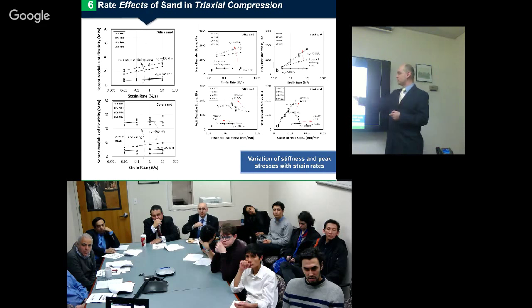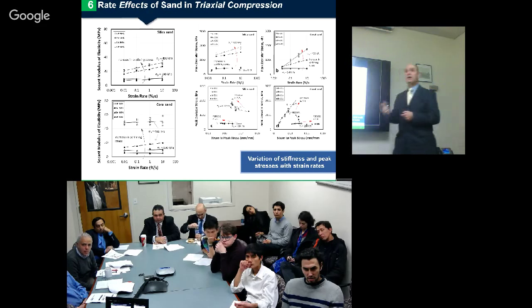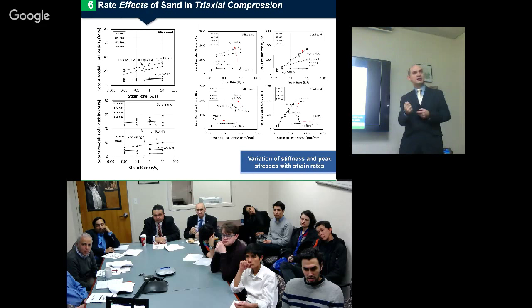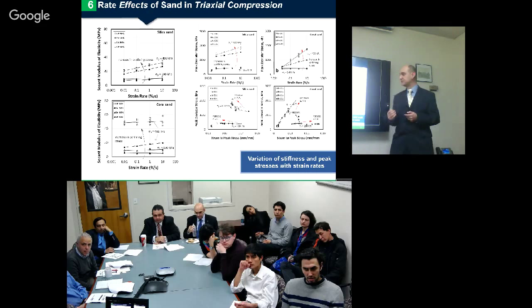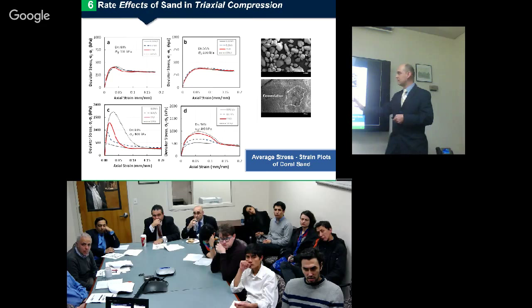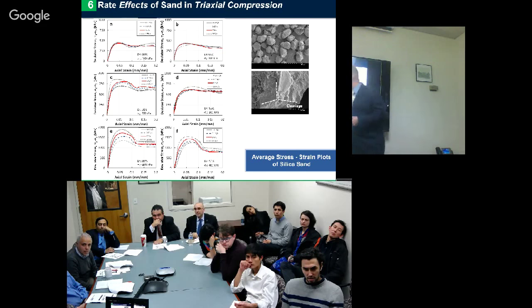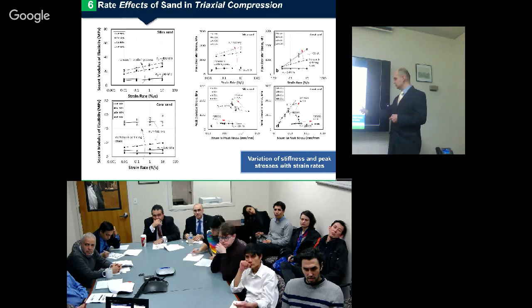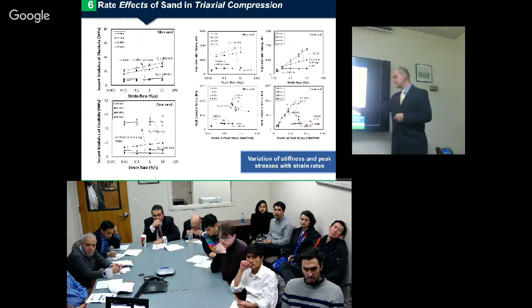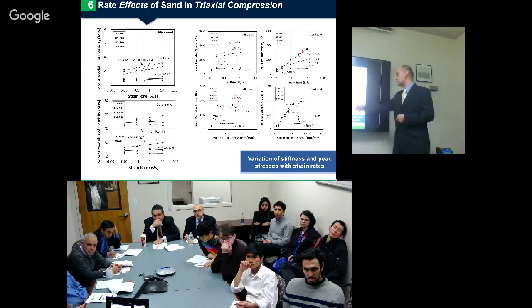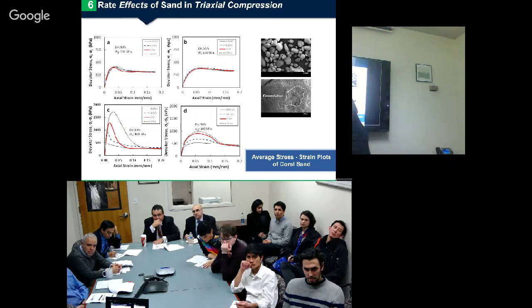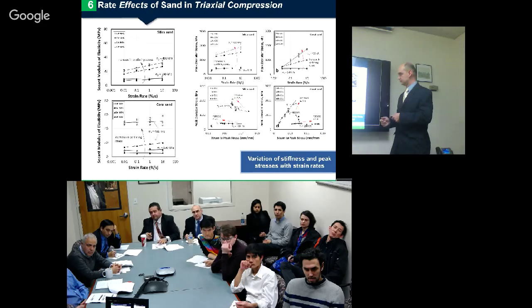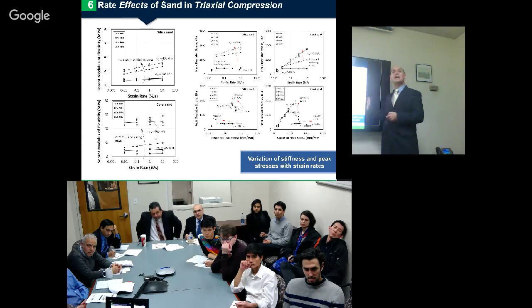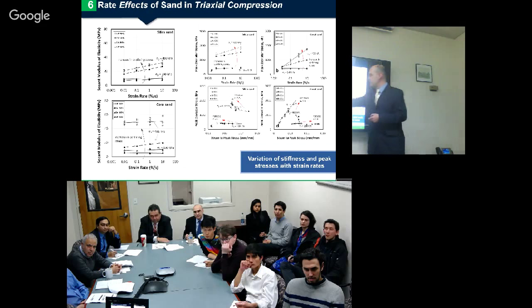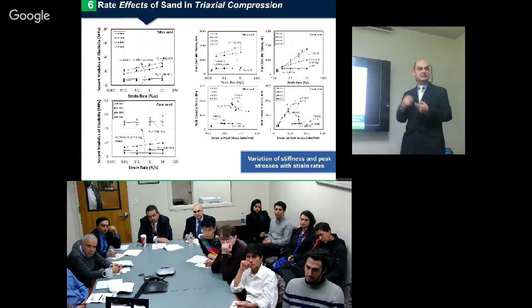In these two figures, we see something special. We have the peak deviator stress, but in the horizontal axis, we have the strain that corresponds to the maximum or peak stress. For silica sand, we see that the peak is moving backwards as the strain rate increases. However, for coral sand, it does the opposite. The actual strain corresponding to the maximum stress increases, from this point to this point to this point. So in this case, the strain to peak stress is increasing, whereas here it's decreasing while the strain rate is increasing.